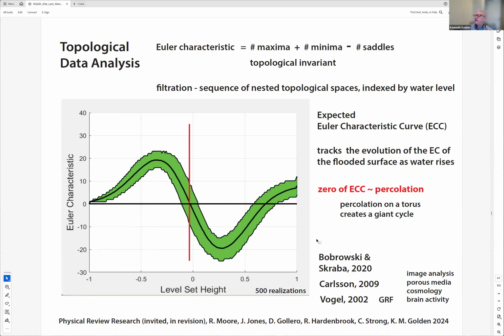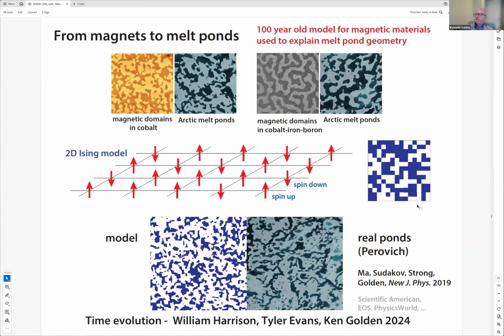And we find an amazing result: as we average over 500 different realizations, the zero of the Euler characteristic curve matches exactly the height of the percolation threshold. And this has been found in some other fields, actually, or at least it's been alluded to, I should say. So anyway, this relates two different fields of mathematics, namely percolation theory and aspects of algebraic topology. And again, another very interesting set of ideas to investigate.